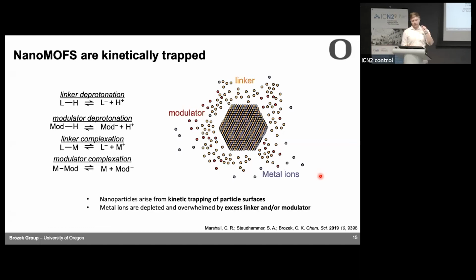And so anything that causes the metals to be closer to each other locally in solution is going to cause you to have bigger particles. In your scale up, if somehow you're not controlling for that... Something we've tried, and haven't published, is syringe injection with stirring and different local concentrations, and we're starting to see that this all impacts polydispersity a lot. But I think what matters most is making sure that you have very slow release of low concentration of metal.